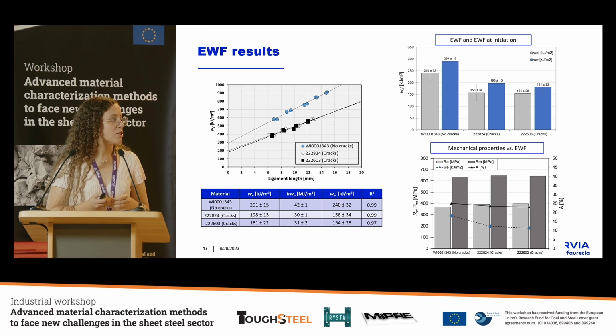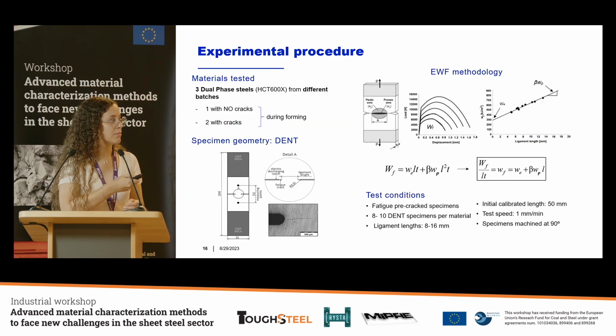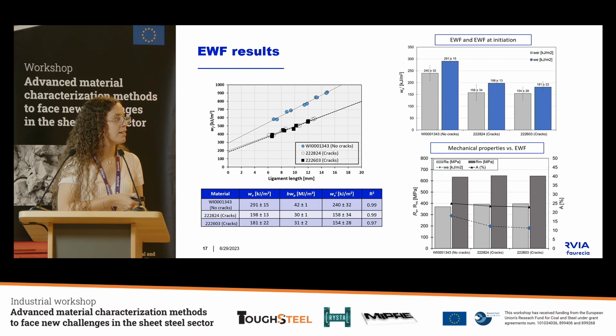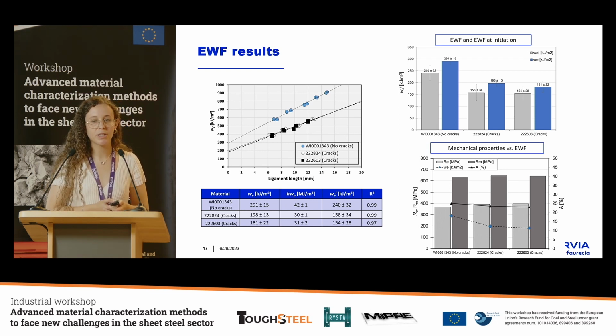This is an interesting result because here in the bottom we can see the comparison between the mechanical properties of these materials, which were almost the same for all 3 materials. However, the fracture toughness results presented this differentiating result, and it coincided with the results that they were finding in their forming performance. Okay, so I think it's a parameter that can easily relate these edge cracking problems that sometimes cannot be predicted with the mechanical properties.